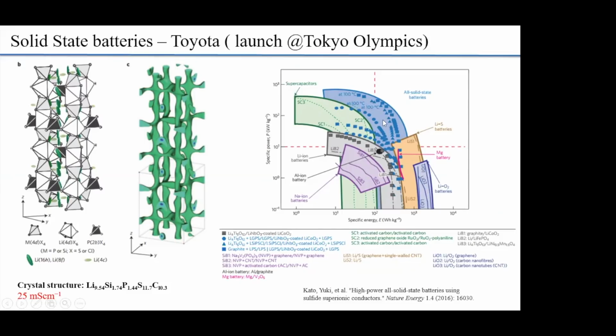And what this graph shows is all solid state battery here. For example, supercapacitors can have really high power density, but their energy density is very low, okay? This is a Ragone plot, and this plot shows where you need to have your energy and power densities. So on one side, you have supercapacitors, with really high power density, but low energy density. You need to cross this red line. You need to have both energy density and power density to be able to use it as an EV battery. So what we are using, lithium ion batteries, is right around this point here. But their prototypes showed solid state batteries with really high power density and also very decent energy density.